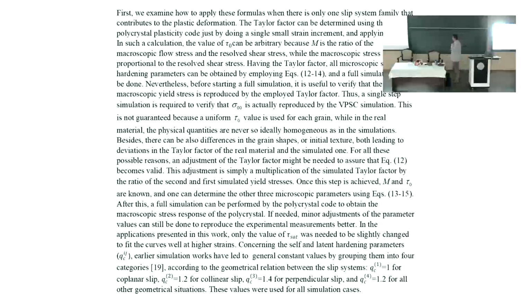So that Q value here has only 4 categories, indexed 1, 2, 3, and 4. This is for self and latent hardening between two slip systems, meaning self-hardening because there is strain in that very same slip system, so strength is increasing. But that slip is making dislocations which are meeting other dislocations made in other slip systems, so there's this cross effect of self-latent hardening. That's why it's basically geometrical. For me, it seems this big matrix, Q,C,I,J, is mostly a geometrical meaning.